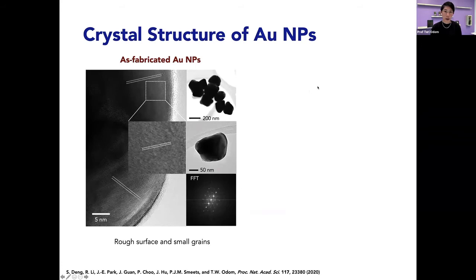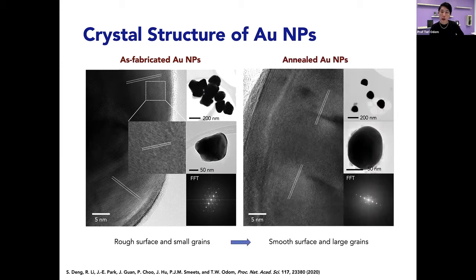So if we evaluate the crystal structure of these gold nanoparticles, we scrape them off with a razor blade onto a transmission electron microscope grid. You can see that the surface is quite rough and the grains are small. You can see this in the broadness of the fast Fourier transform. If we look at the annealed particles, you can see that the grains are much, much larger and the surface structure is quite smooth. And I love this image here. You can see this is where the substrate was, and we have this beautiful hemispherical type shape.